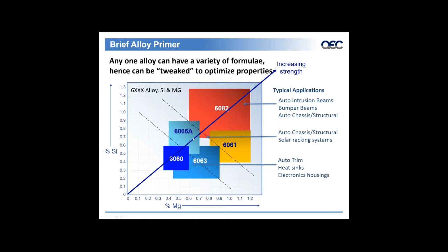When we rise in silicon and magnesium, we get into a 6005A, some overlap with 6082, an overlap of 63, and an overlap of 61. We typically see these alloys utilized in auto chassis, structural, and solar racking type systems, where structural integrity matters. This band of alloys can be quenched either by air, an air-water mixture, or a full water wall quench. Again, this band of alloys is increasing relative to the percent magnesium and percent silicon.